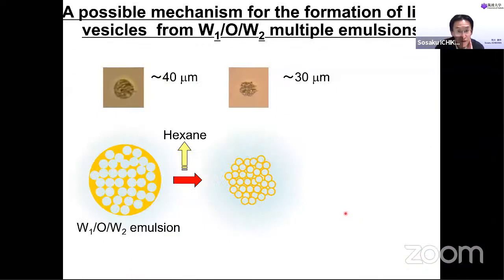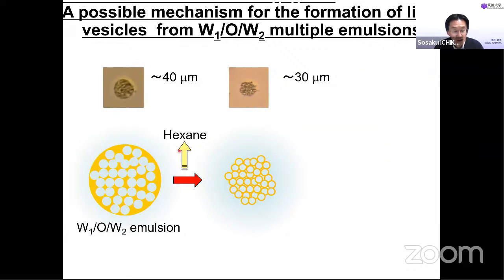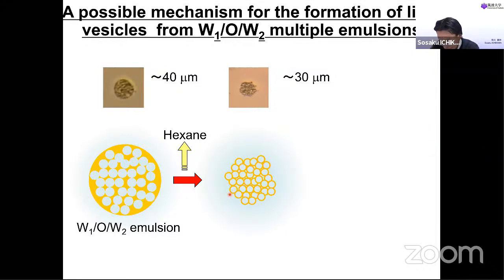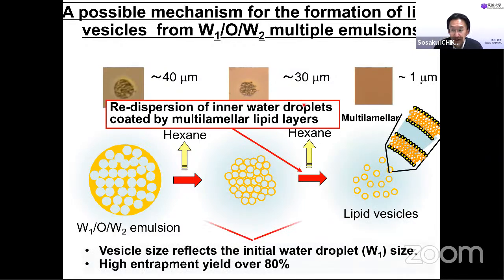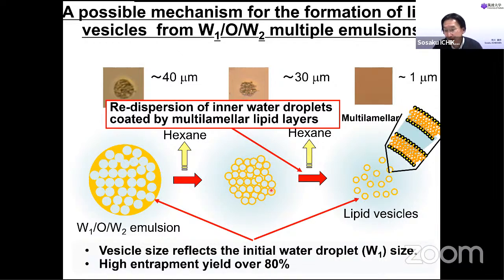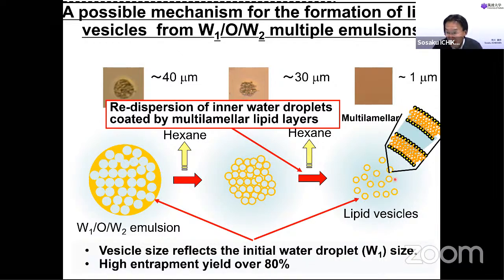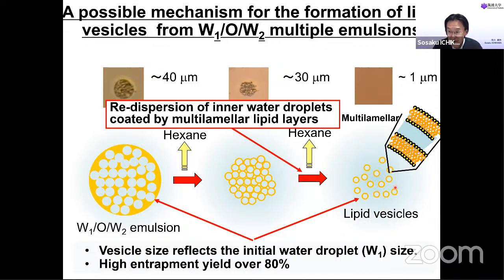So this is a microscopic observation during the formation from W/O/W emulsion here. Then after the hexane evaporation, we can observe this kind of aggregate of lipid vesicle. After that, this small lipid vesicle disperses like this. So then we get the lipid vesicle containing some materials inside it.